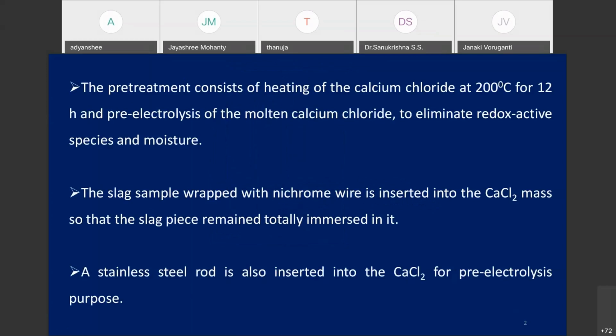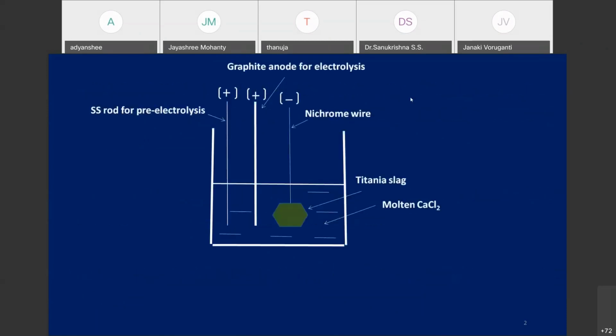The slag sample, wrapped with nichrome wire, is inserted into the CaCl2 mass so that the slag piece remains totally immersed in it. Then a stainless steel rod is also inserted into the CaCl2 for the pre-electrolysis purpose. Pre-electrolysis is carried out at 2 volt. First you carry out like this. Usually we carry out pre-electrolysis for 15 minutes.